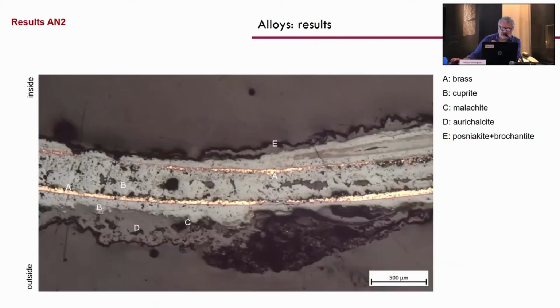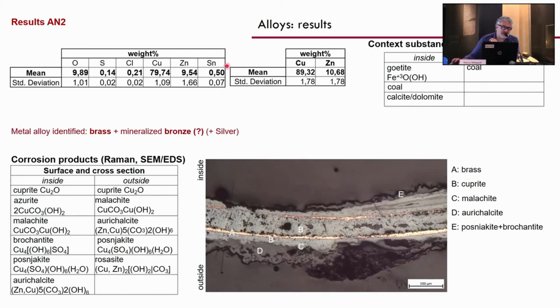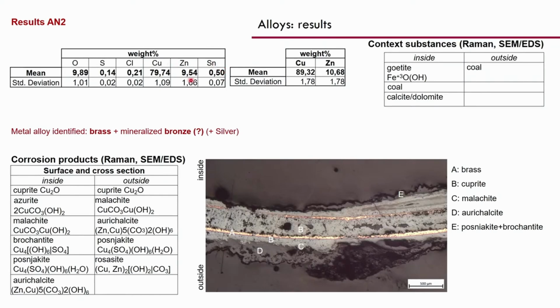So these are the results that we obtained on another cross-section from the Archaeological Museum of Naples. And as you can see, we found a brass characterized by these two slices of metallic brass. The metallic alloy is still present, and the slices are perfectly parallel. And as you see, we have almost 300 microns of thickness between these two slices of brass. And for the analysis, as Claudia Pelosi analyzed, we see in the brass, of course, the presence of zinc, around 10%, but also the presence of tin.